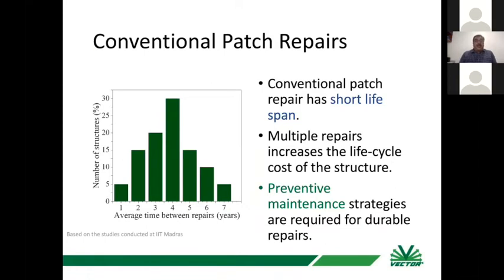Like there was a study carried out along with IIT Madras, and it was found that the majority of structures fail. The repair part fails once corrosion has initiated, and in the propagation time when we repair it, it fails within 4 to 5 years, in the majority of structures.